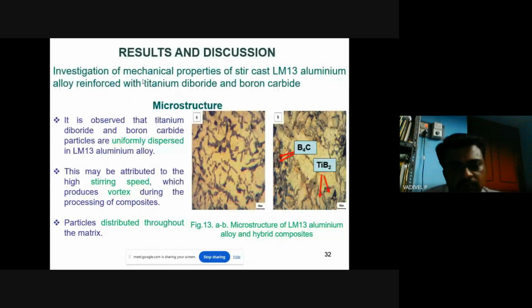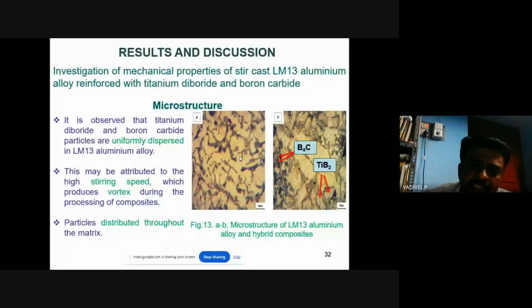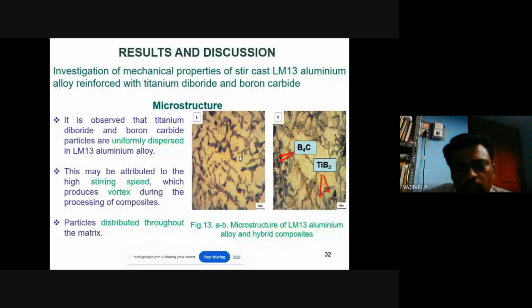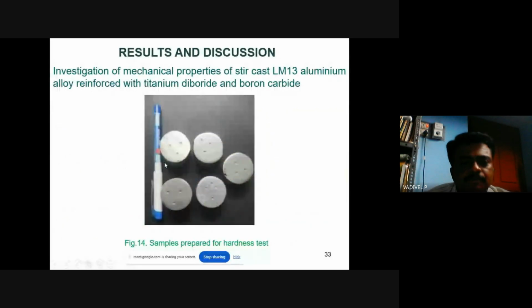So the microstructure study reveals that the dispersion, the mixing of the aluminum matrix and the reinforcement, is uniform throughout the matrix. To confirm this mixing or dispersion, we have done the microstructure study for several samples. And the samples were prepared for the hardness test. As already mentioned, the Brinell hardness test has been done for that.